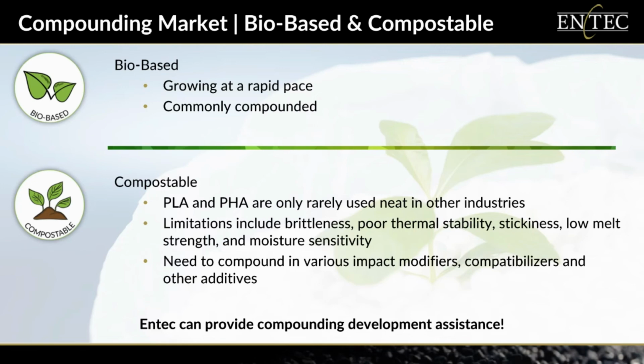In addition, these materials tend to absorb a lot of moisture, so proper drying is critical to minimize degradation, which can lead to poor properties, viscosity loss, and loss of melt strength. And as more and more compounders start to compound these materials, especially the PLA and PHA types, it will drive the need for compounding development assistance, which Entec can provide.